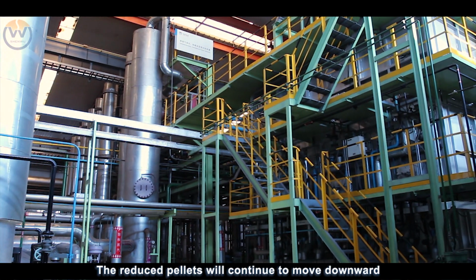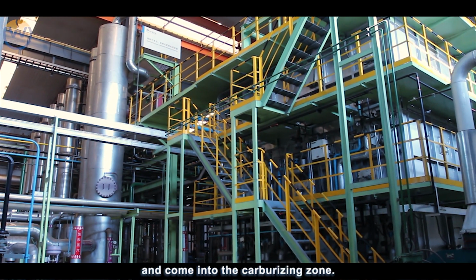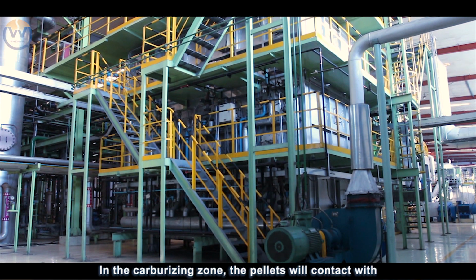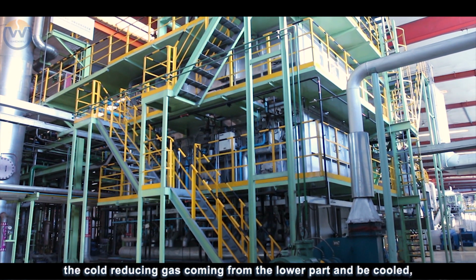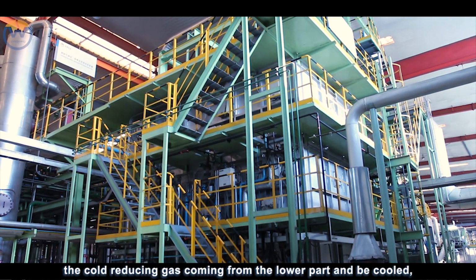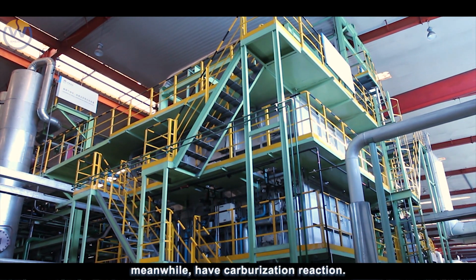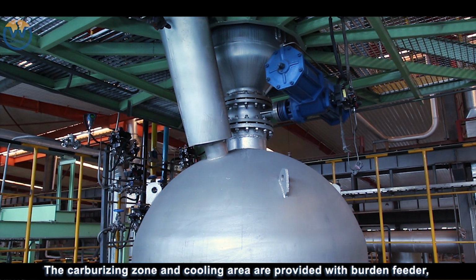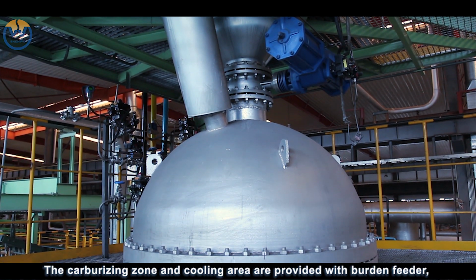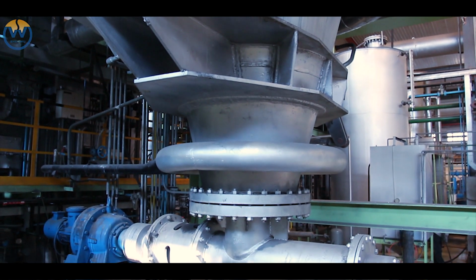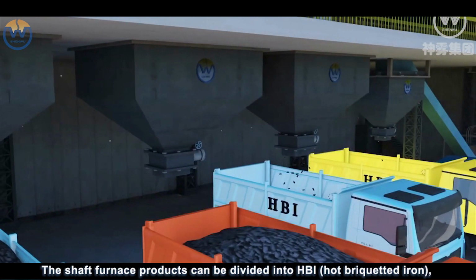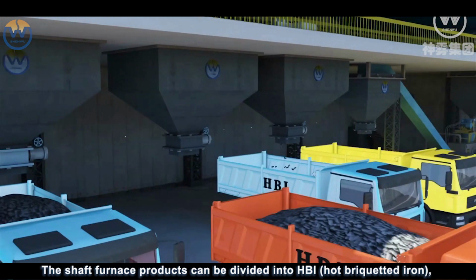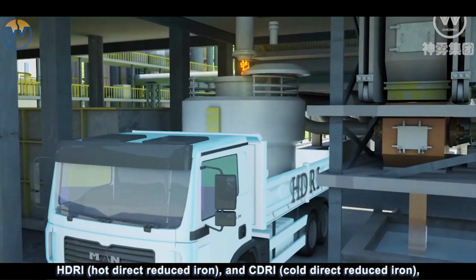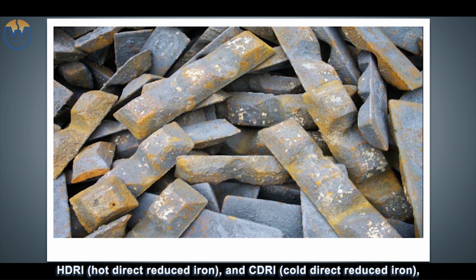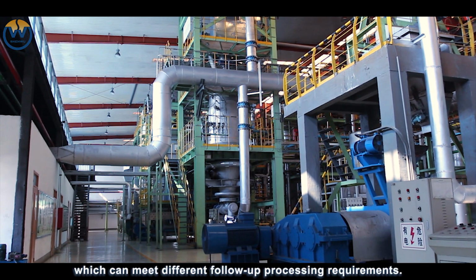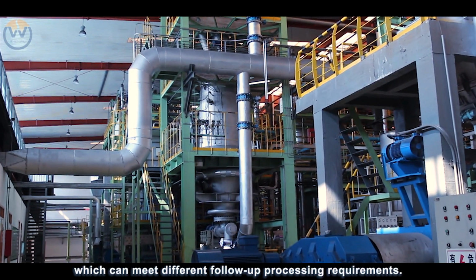The reduced pellets will continue to move downward and come into the carburizing zone. In the carburizing zone, the pellets will contact with the cold reducing gas coming from the lower part and be cooled. Meanwhile, they have carburization reaction. The carburizing zone and cooling area are provided with burden feeder, which can prevent the burden bond. The shaft furnace products can be divided into HBI, hot briquetted iron, HDRI, hot direct reduced iron, and CDRI, cold direct reduced iron, which can meet different follow-up processing requirements.